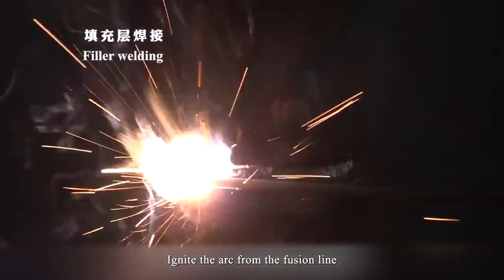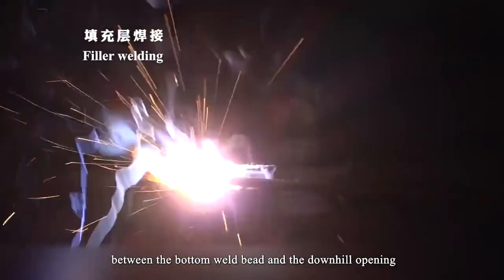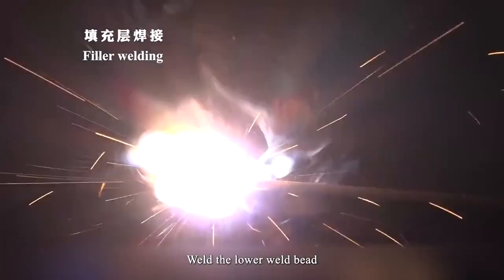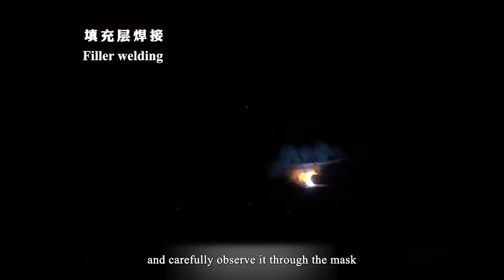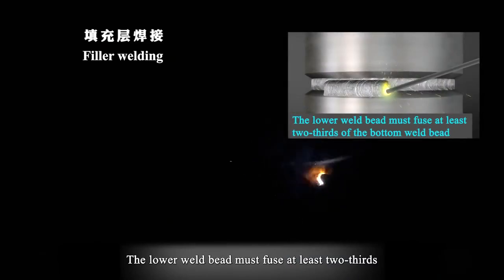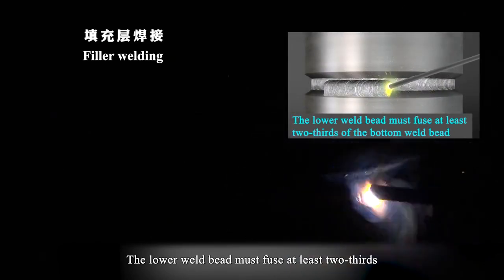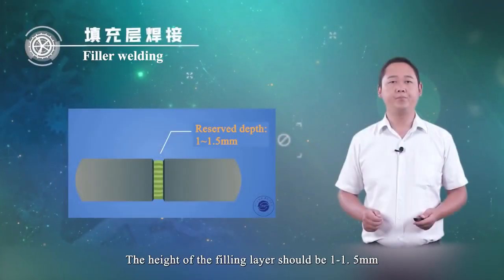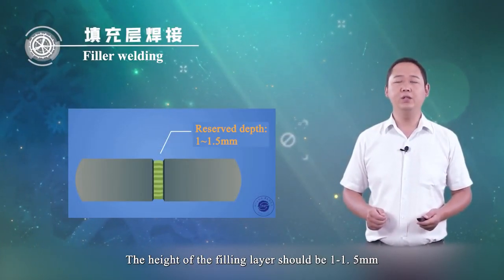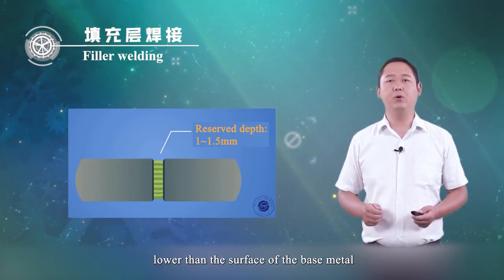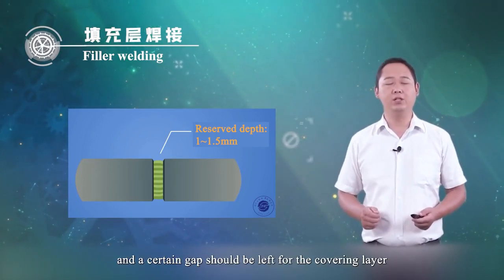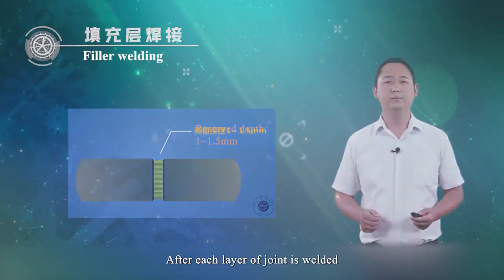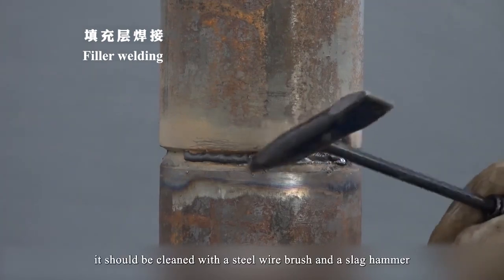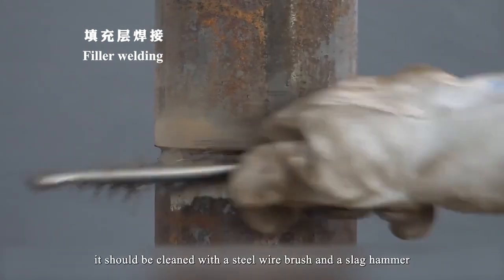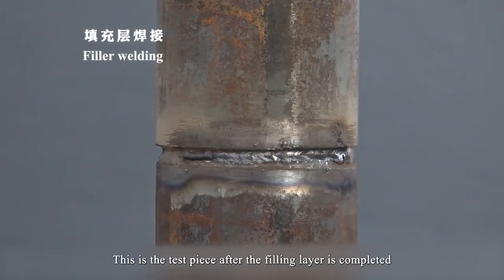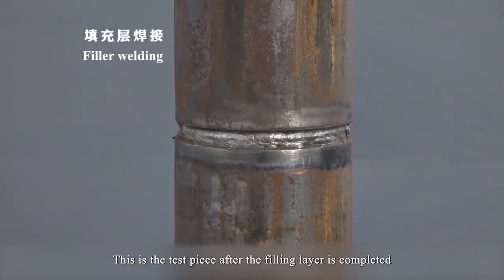Ignite the arc from the fusion line between the bottom weld bead and the downhill opening. Weld the lower weld bead and carefully observe it through the mask. The lower weld bead must fuse at least 2/3 of the bottom weld bead. The height of the filling layer should be 1 to 1.5 mm lower than the surface of the base metal, and a certain gap should be left from the covering layer. After each layer of weld is welded, it should be cleaned with a steel wire brush and a slag hammer. This is the test piece after the filling layer is complete.